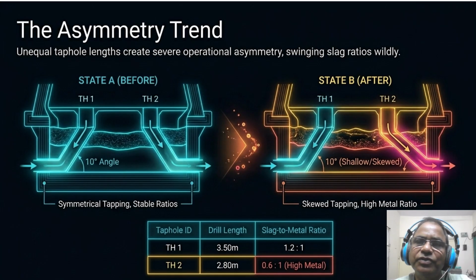State A on the left shows a symmetrical tapping with two 3.5 meter tapholes. The slag to metal ratio is a stable 1.2 to 1.0. Now look at state B. Taphole 2 has a shortened 2.8 meter length. Notice the skewed tapping icon. The liquid flow is now biased toward the shorter, easier path. This swings your slag ratio widely, dropping taphole 2 down to a 0.6 to 1 ratio. This means you are pulling mostly metal and leaving the slag behind.